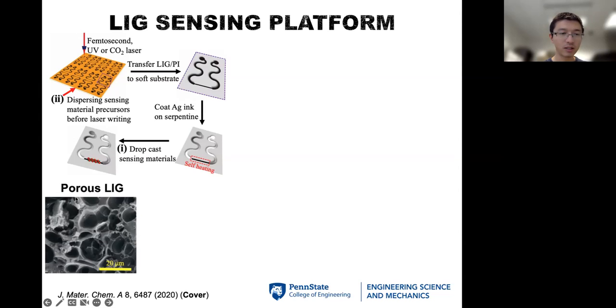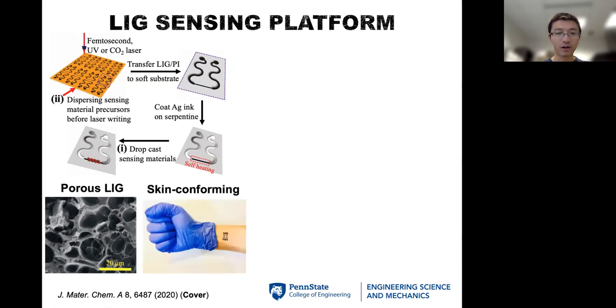And the highly porous structure with the big microstructure pores from a few microns to a few tens of microns can facilitate transport of the gas molecule, moisture, through the layer, and also you get to see the smaller size, a few nanometers to a few tens of nanometers on the cellular wall. So that can also increase the sensitivity and transport of the gas biomolecule. And through that process, we'll be able to decorate the surface further with a gas-sensitive nanomaterial and be able to detect the target biomarker. And everything will be wearable, so we can deploy this on the skin surface.